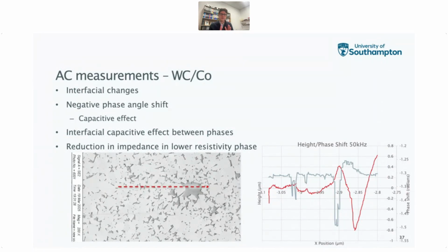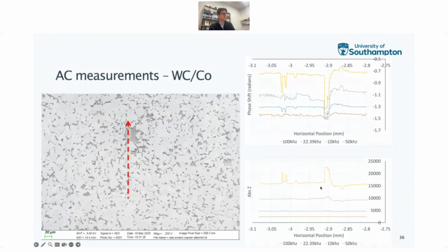We think we may be seeing an interfacial capacitive effect occurring between the two phases as we're approaching the different interfaces, and then once we're into the second phase, the cobalt phase, we're seeing a drop in the absolute impedance, as we might expect from a low resistivity material.